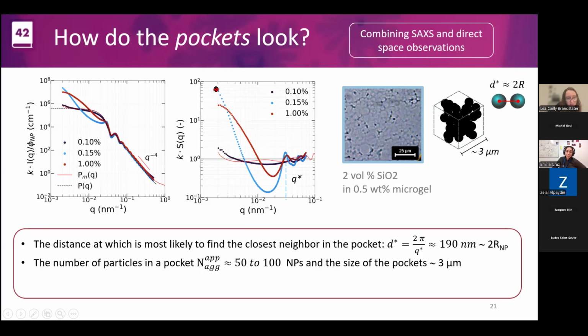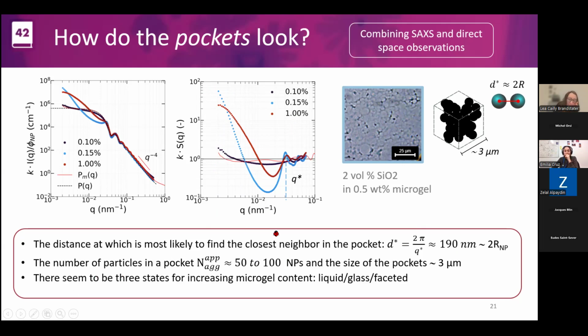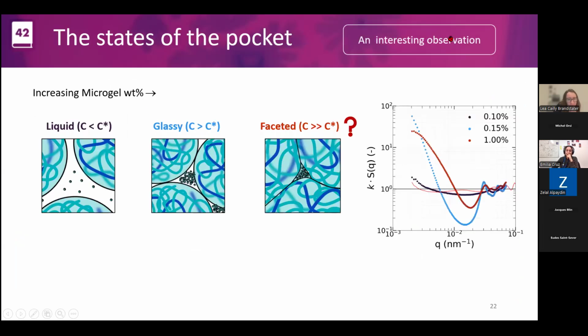And also, because we know that this is the highest length scale that we can probe, the pockets are around 3 micrometers or maybe a bit higher. And this higher microgel concentration revealed that there seem to be 3 states for increasing microgel content, actually. There's the liquid state, the glass state, and a faceted state. Let's take a look into that. It's an interesting observation that we've made, but we only have that one sample that's behaving this way so far, so we would need to prepare a few more.